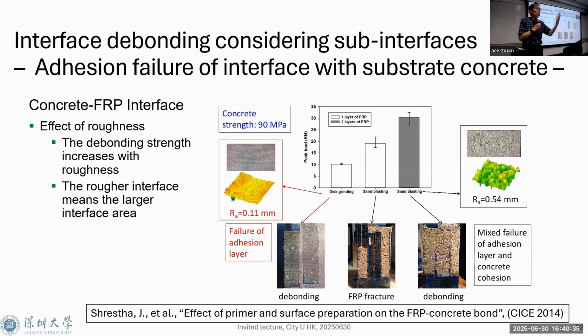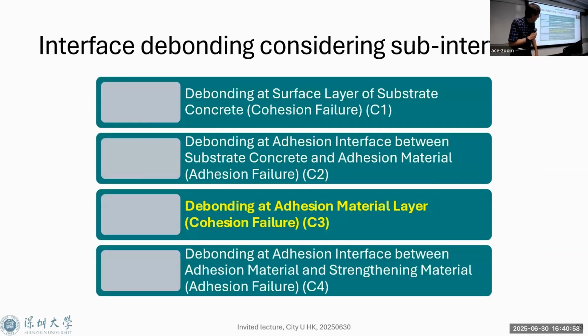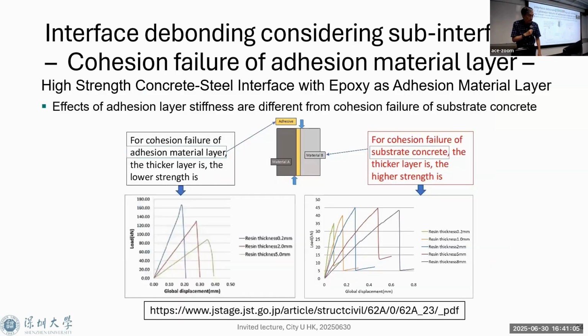This is different from the Ueda case. In the Ueda case, the substrate concrete debonds. But in this one, it is an adhesion interface debonding. So surface roughness only affects the case of a real interface, an adhesion interface. Right, the debonding at the adhesion material layer. So the debonding takes place this time within the adhesion layer, within this one.